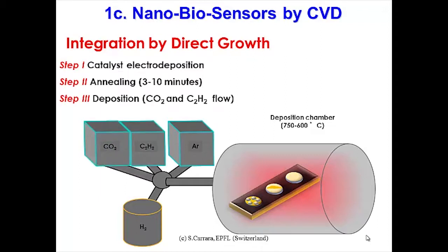And then by using these two carriers, she injected carbon in the chamber in order to obtain the growth of carbon nanotube. We obtained not only carbon nanotube, but also graphene nanoflowers, and also structures that are a mixture between graphene nanoflowers and carbon nanotubes.